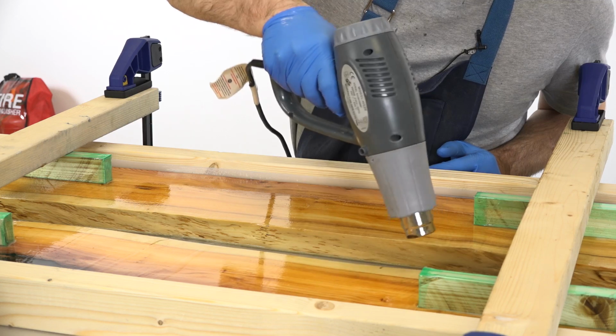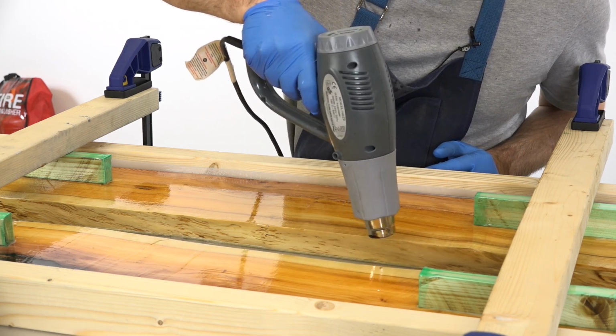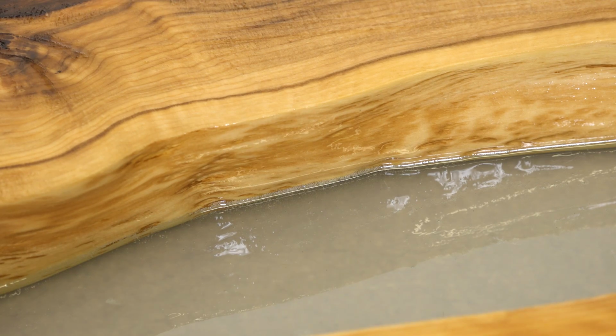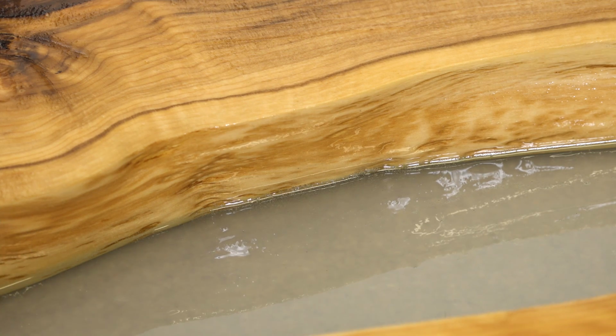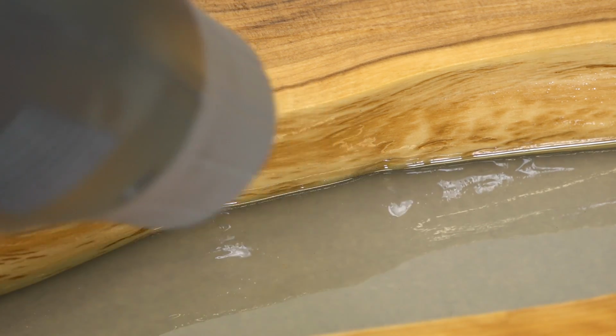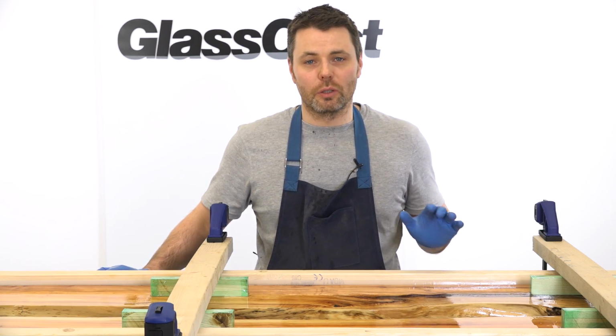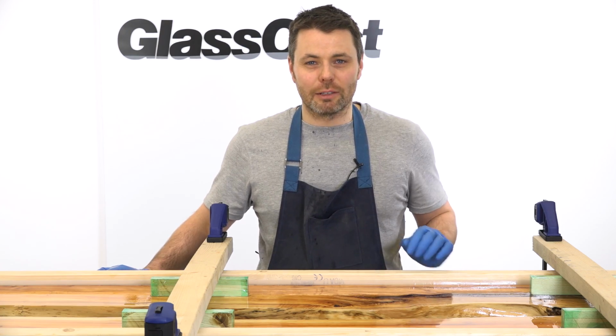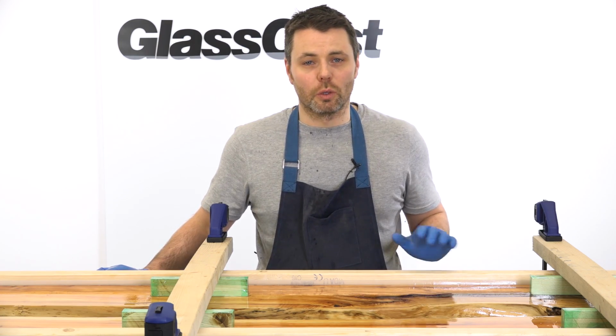GlassCast 50 is very good at releasing trapped air without any help, but it's still a good idea to use some light action with a heat gun to help the process along. We just need to leave this first layer to cure to what we call the B stage. That'll take around 12 hours at 20 degrees, so we'll come back to this in the morning.